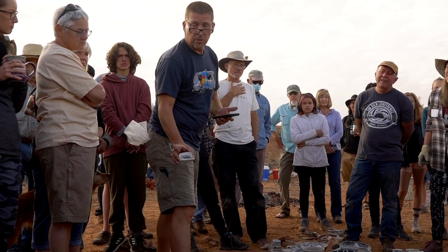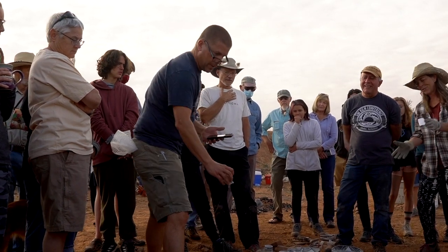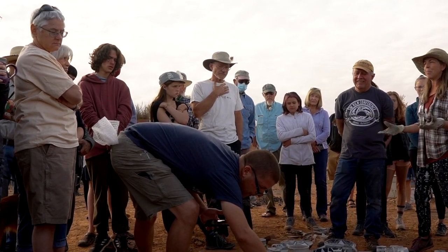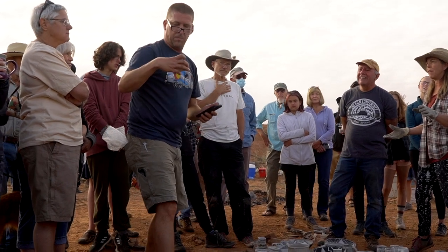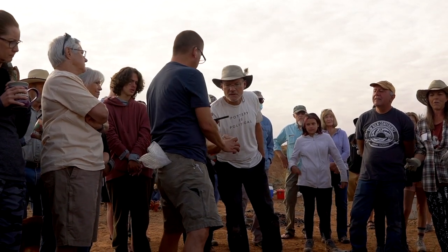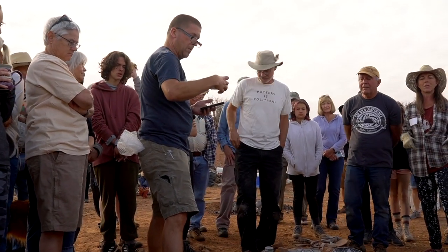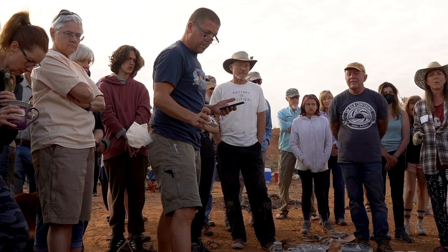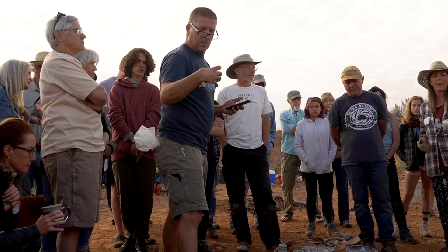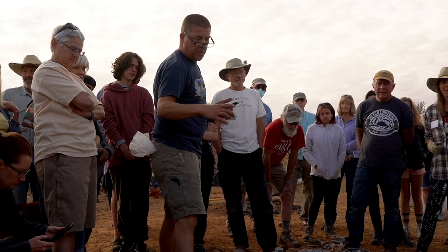Whoa. So where are we at? 875. 895. This one right here. Right in the core. Guys, this is really a big deal, because to even get near 850, 900 Celsius in these kilns, you are working your tail off. That was the reason for the setters and the helpers. That's the reason I was leaving the crib so open, so I could jerk that air back in to reignite those coals. The other middle one right down is similar to the other one I showed you.